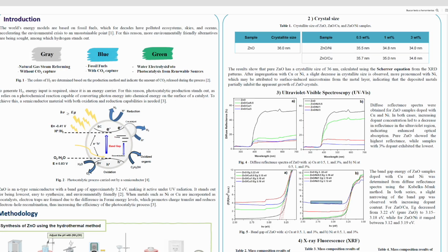For this, we need a semiconductor with the optimal characteristics to act as both a reducer and an oxidizer, and to handle the oxidation part. However, for this chemical reaction to effectively take place, photocatalysis crucially requires that each band edge possesses a very precise position within the energy spectrum. So on the reduction side, we need a minimum energy level of minus 0.41 volts. And on the oxidation side, this energy level is 0.83 volts.